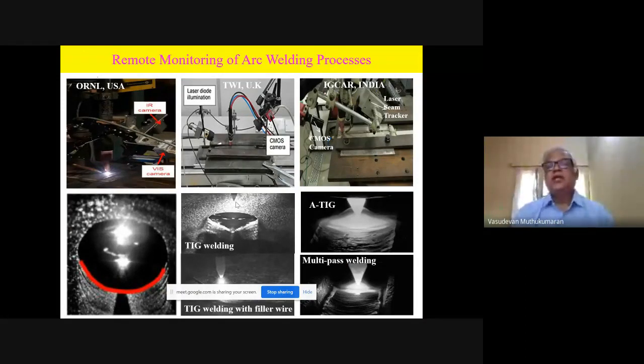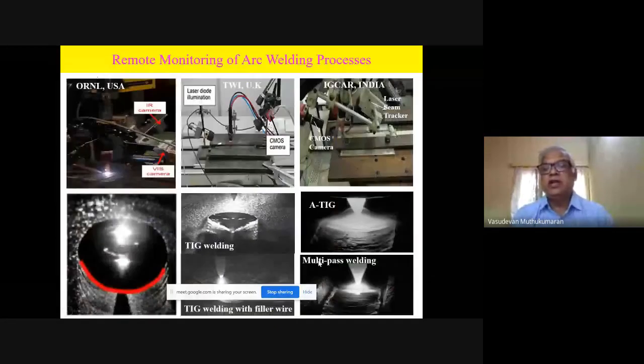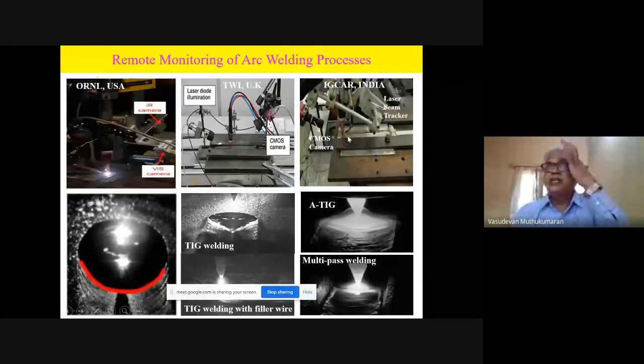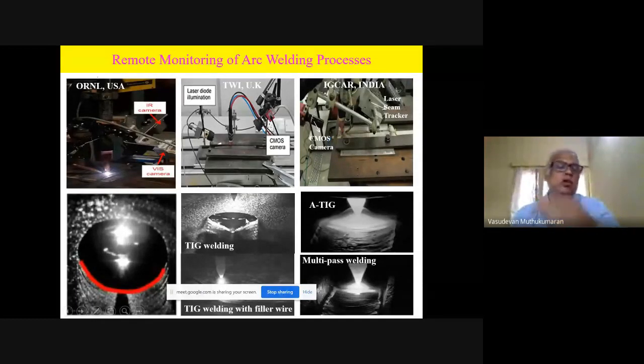Whereas in our case, the camera we have has only 60 dB dynamic range of brightness. With the arc, the arc effect is still seen in the images. You can see it during TIG welding, and even in multipass welding you can see the grooves. We need to use 120 dB cameras to nullify the arc effect. Then only will the arc be totally not seen. Then we can use the weld pool precisely for image processing and further development of a control algorithm to control depth of penetration and bead width.